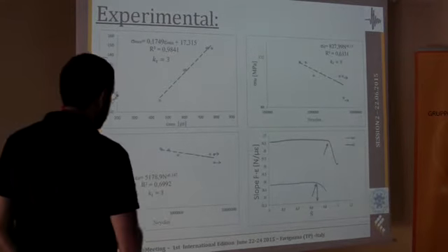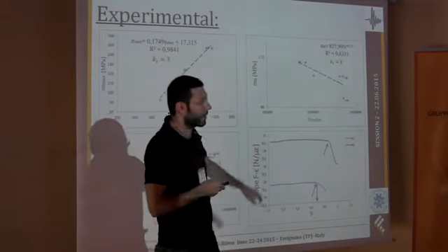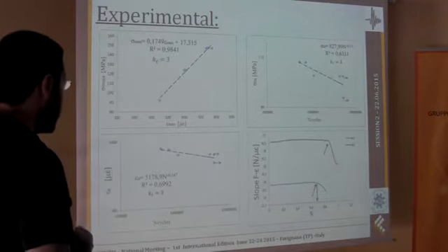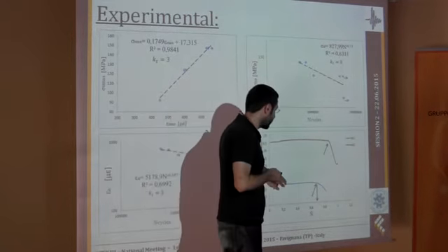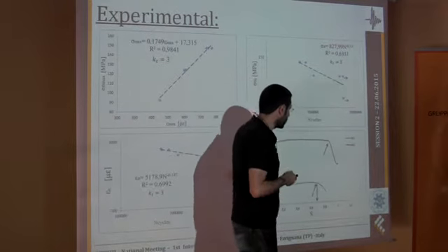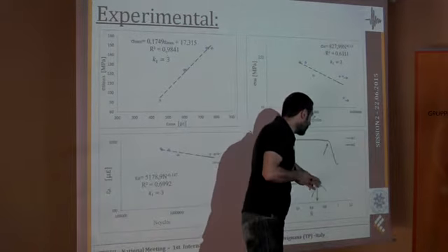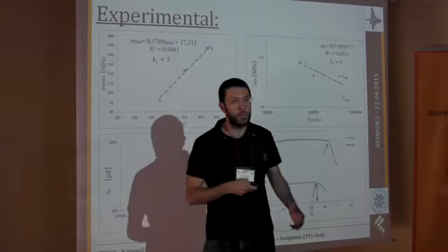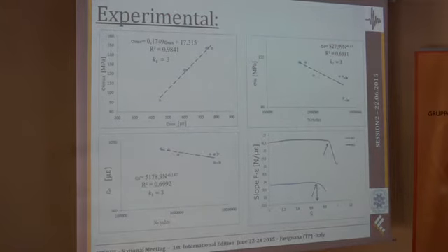And also, if you look to the slope, this is the slope of the load versus strain curve, as it was determined by the strain gauges. And as you can see, this slope stays almost constant during all the tests, and when we arrive at about 70% of the total test time, we start to observe a decrease in this slope. And, of course, this decreasing is observed first from the strain gauge, which is nearest to the location where the crack initially propagated.